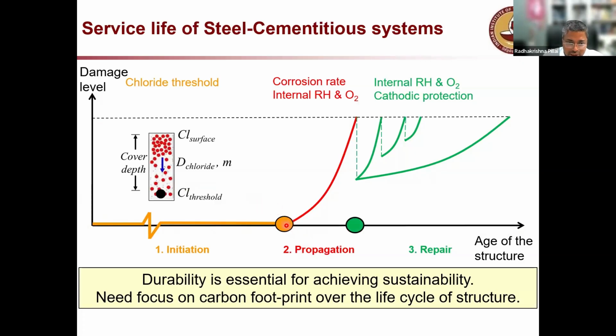Now, once the steel starts corroding, then in a few years, you will see that there is significant cracking, spalling, etc. And this dashed line over here indicates that the damage level has reached a critical level. Then what you do, you will actually go for a repair. That way your damage level is reduced. Then again, the structure is in the same condition, and if the repair is not done in a proper way, you will again, after a few years, go and do the repair in the same place. So multiple repairs you will keep on doing, which is going to cost you a lot of money.